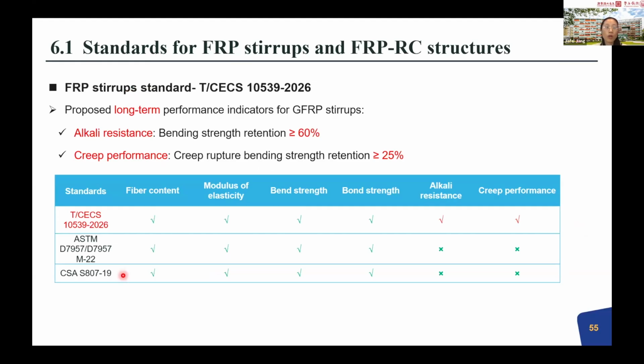And here, we involve the fiber content, modulus of elasticity, and bend strength, especially to regulate the minimum reinforcement ratio, and also the bond strength, because we need to make sure it has the contribution to the shear and to the torsion. And then most importantly, we involve the long-term coefficient related to alkali resistance and creep performance.